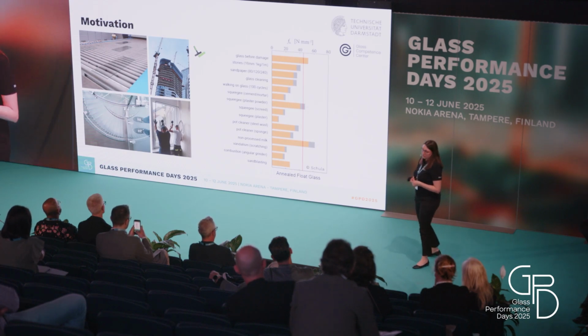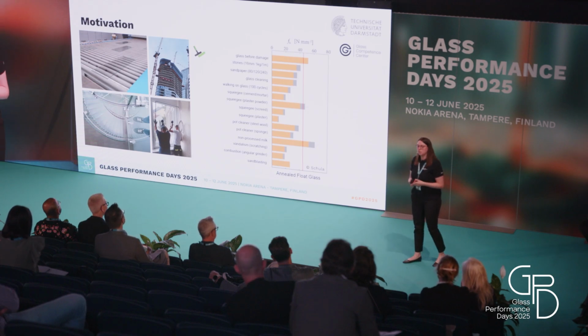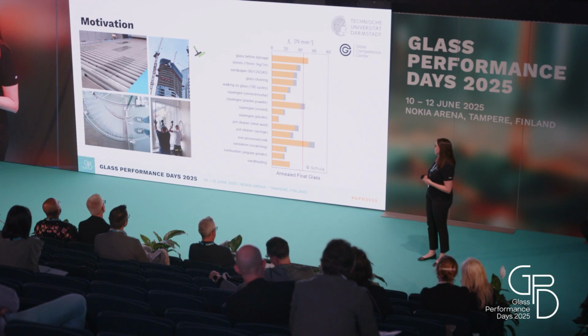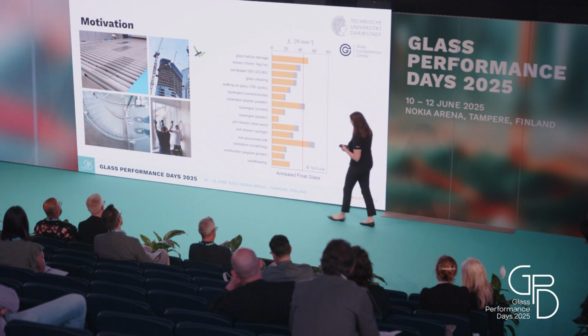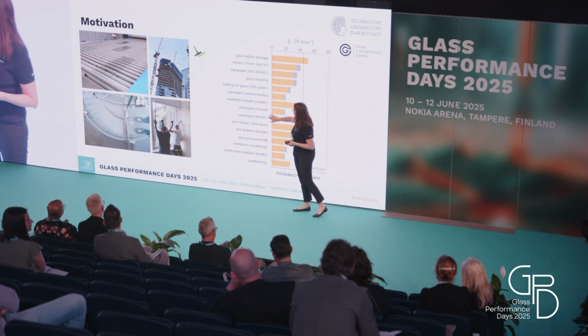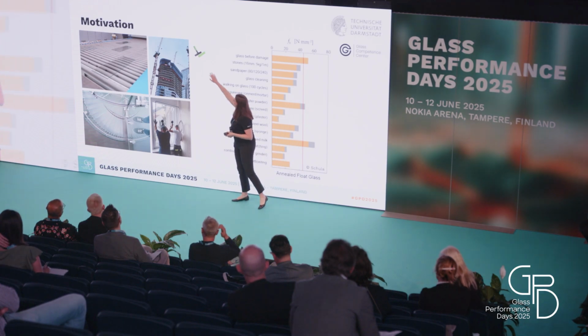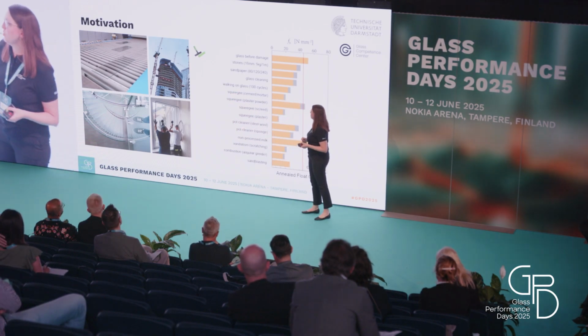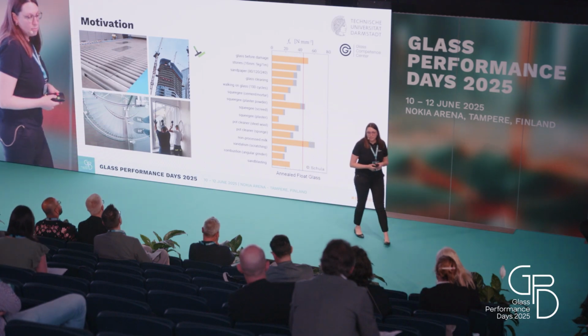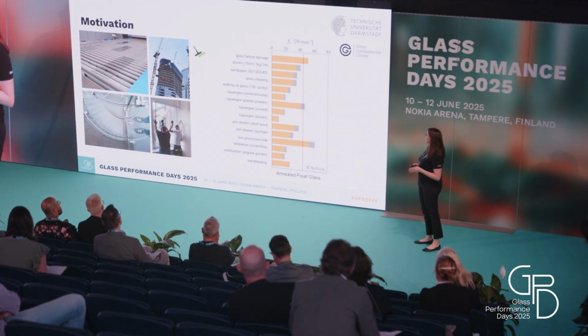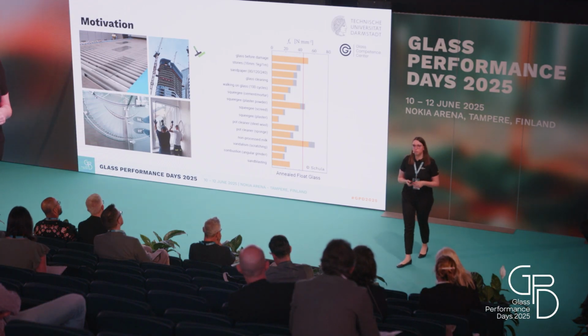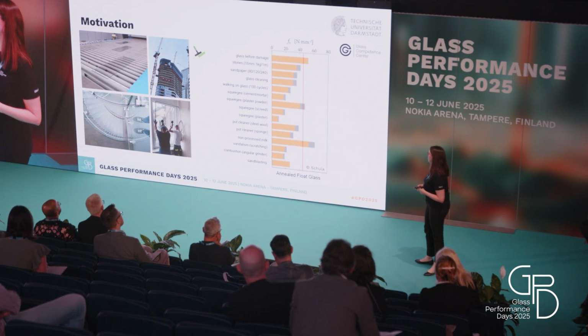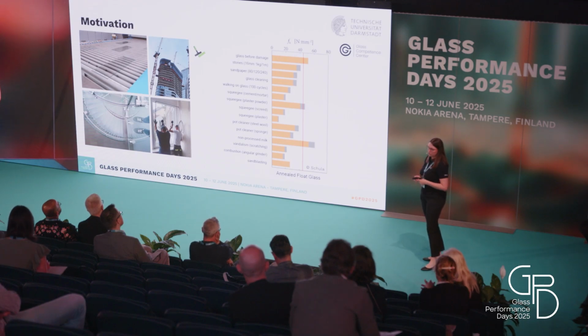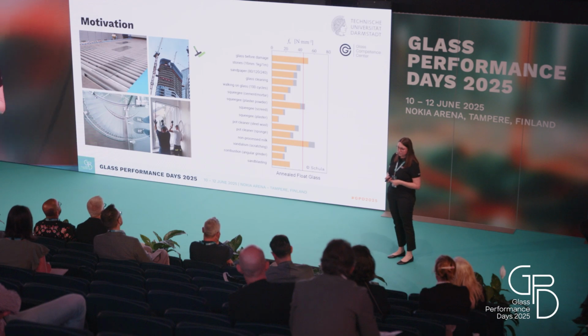And a former colleague from our institute, Sebastian Schuler, did a lot of investigations on the strength of glass which was damaged. I want to highlight here only one or two cases. So here we have glass that was treated with a squeegee. A squeegee is this green tool here at the top, and it was used to remove screed or plaster from the glass. And we see that those glasses only had a strength of around 10 to 20 megapascal, which is much lower than the characteristic strength value of new annealed glass that we find in standards, which is usually 45 megapascals.